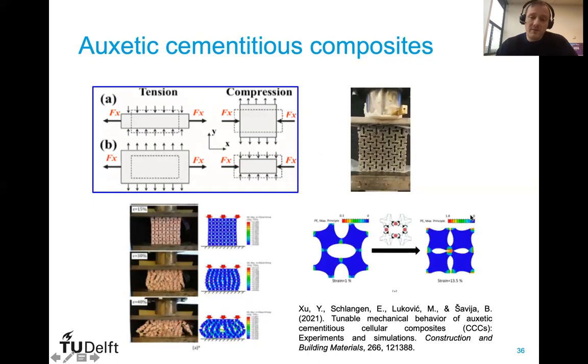So here I will show you a video of what we achieved. We created a certain pattern, and with a fiber reinforced material, we were actually able to achieve a material that contracts laterally upon compression, so it has auxetic properties. However, the mechanism of auxeticity in cementitious materials is different than that of polymer or rubber-like materials that are commonly used in the literature.